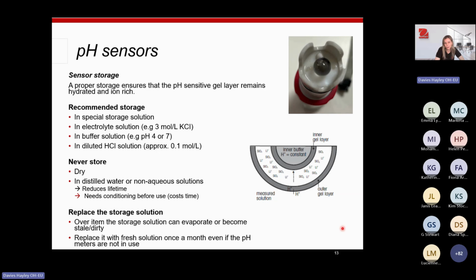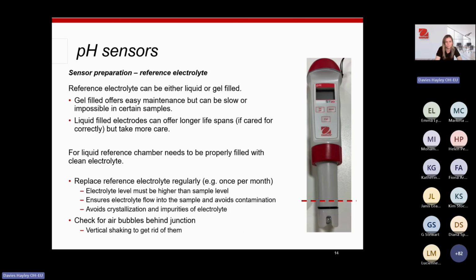Replace the storage solution. Over time it can evaporate, it can become stale, it can be dirty, it can get bacteria inside. So it is recommended to replace the storage solution once a month with fresh solution, even if the meters are not in use. It's always good practice to not top up. We would replace it: wash out the wetting cap, pop some fresh solution in, and do that once a month. This is all to get the best and the longest life out of your electrodes.